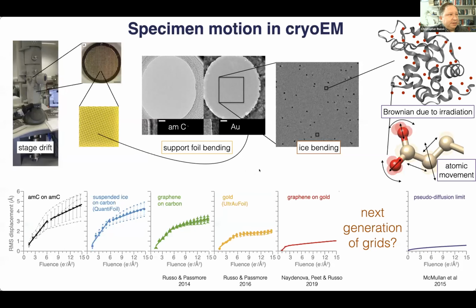And that's because not all of the movement was removed. So the movie you saw there was showing the difference in the foil movement. But when you track gold nanoparticles in thin layers of ice within the hole here, you can see that even if the edge of the foil is completely motionless to better than an angstrom, you can see the lattice right in the foil, the particles inside the foil are actually moving. And not only that, they're moving in a correlated way.